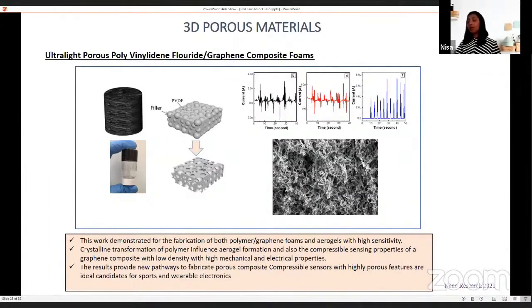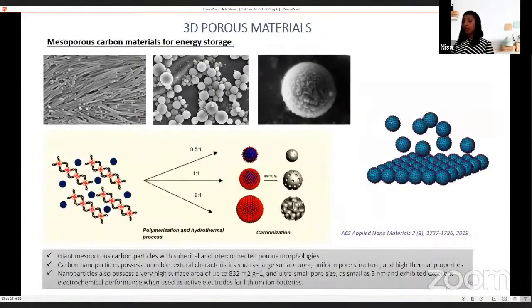So in the study, we demonstrated how the crystalline transformation of PVDF influences aerogel formation. And this material exhibited compressive sensing properties. We were also interested to look at structural features to make porous carbon materials. So in this particular study, we followed a soft templating process by using block polymers. So here the target was to make tunable carbon nanospheres with uniform porous structures.